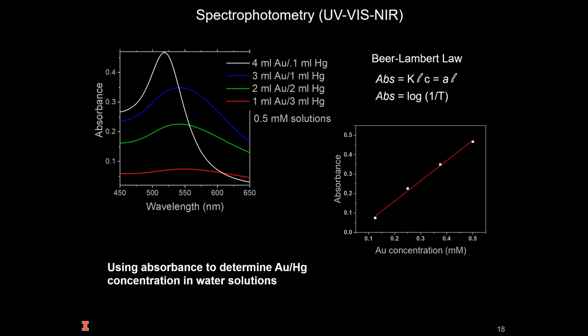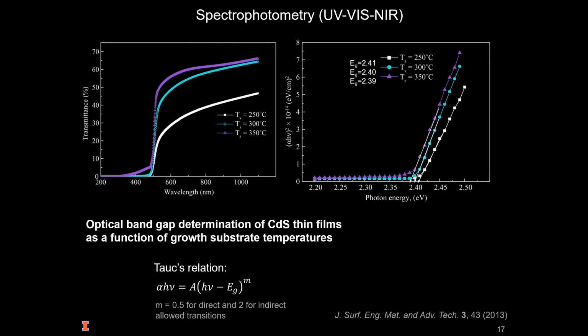The photoluminescence is a more direct measurement of the band gap. With spectrophotometry, you basically have to fit this to a curve to obtain your band gap in the end. The photoluminescence is a direct measurement of that — the band gap transition, that energy the photons will have when they exit the sample.